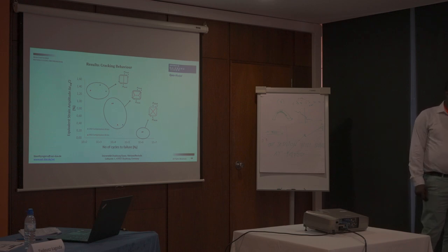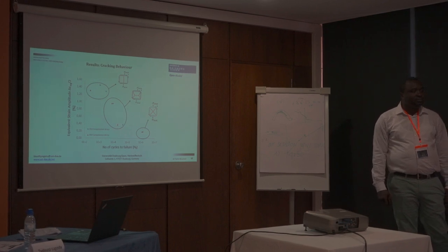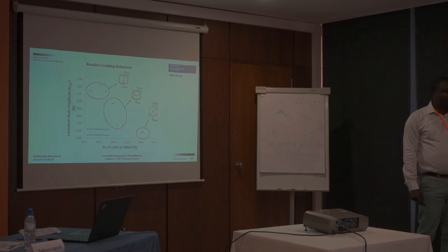Yeah, as compared. So it depends on a lot of things, on the dislocation density that you create, but also on the thermal conductivity. Of course. But the basic mechanism of material heating up in fatigue testing, I think that's it, unless you're doing something very specific. You're putting in mechanical energy, and it's being dissipated on the micro level by dislocations that move over glide planes and move back, and that's plastic dissipation. That leads to heat locally, and that seems to correlate with the picture you showed.